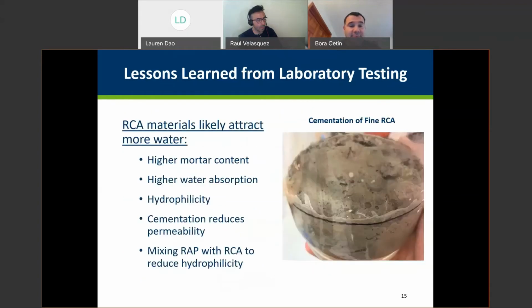Next slide, please. And one thing, especially when we were running the hydraulic conductivity test with the fine RCA, we realized RCA materials attract more water, and that is directly related to the water absorption. So they absorb a lot of water, and if you have higher mortar content, that will mean higher absorption. And one thing that we saw with the water repellent studies is that RCA materials have very high hydrophilicity, so they like water, they absorb the water.